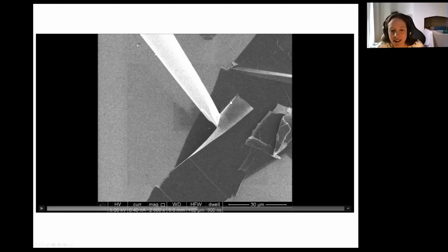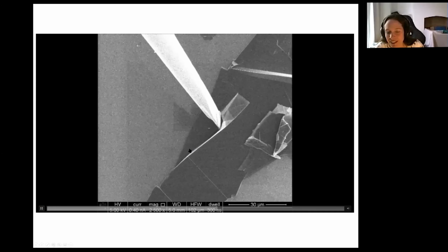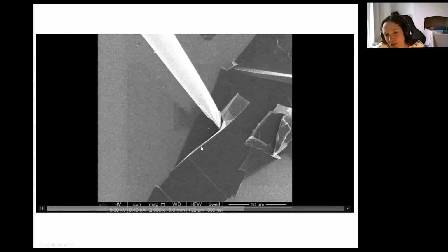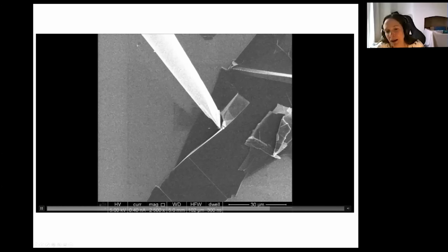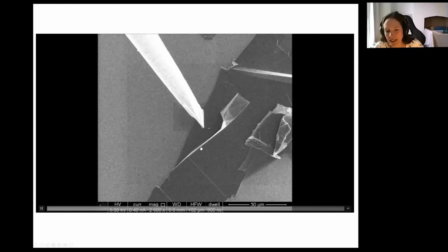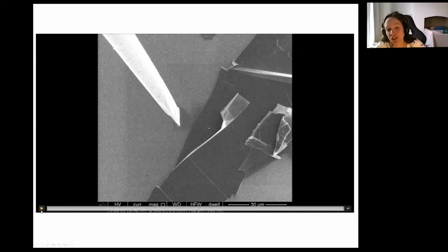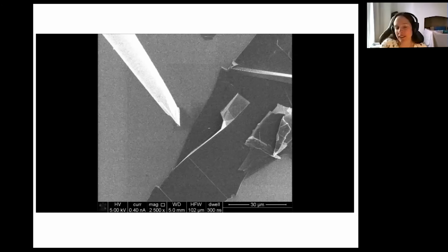And as we exfoliate this upper layer using the micromanipulator tip inside the SEM, you can see that underneath the exfoliated layer, if your video is good enough, we've created an extra one of these line defects that's propagating underneath that exfoliated sheet. Now, these types of features are ubiquitous, so everybody who has done exfoliation of 2D crystals sees them. If you talk to the people who make electrical devices from these crystals, they will tell you that you have to avoid them. We don't want to go too close to these types of structural defects, or the electronic behavior of your material will be degraded, will be reduced.